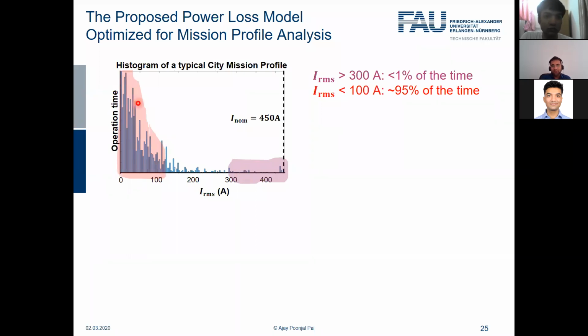Whereas less than 100 ampere of current is more than 95% of the time. So for me, the conclusion or the message is that the inverter is operating more than 95% of the time at less than 1/4 of the nominal current. So this means that the automotive traction inverter has to be optimized for this region, because this is the most frequent operating point of the inverter. And if you remember a few slides back where I showed the IGBT versus MOSFET behavior, we have to recollect that the silicon carbide MOSFET performs especially better in this light load condition, which is very good for the traction inverter. So therefore, silicon carbide MOSFET offers a very good performance in this region, but we will anyways verify it later.